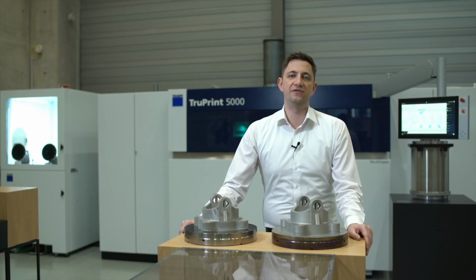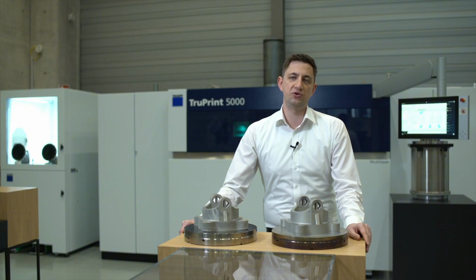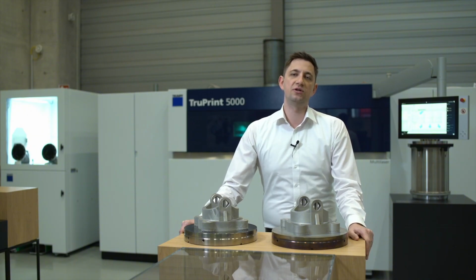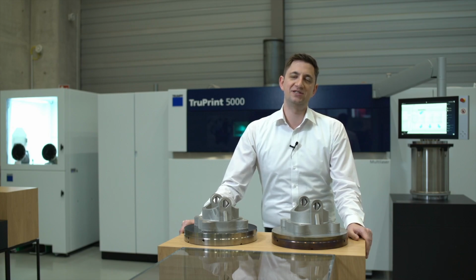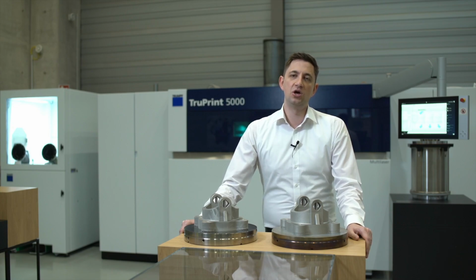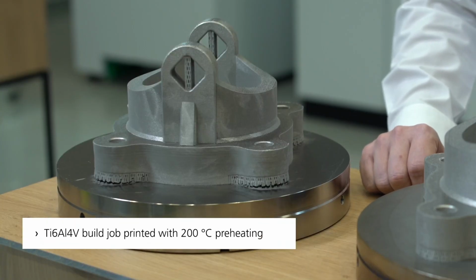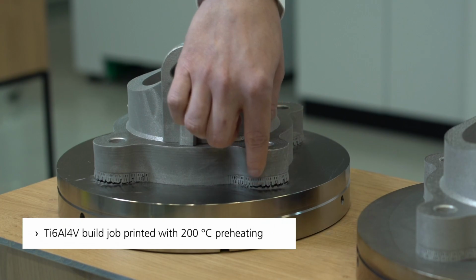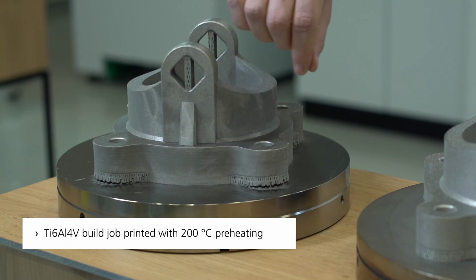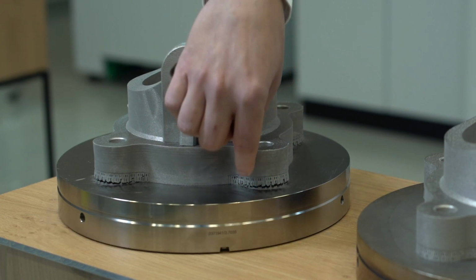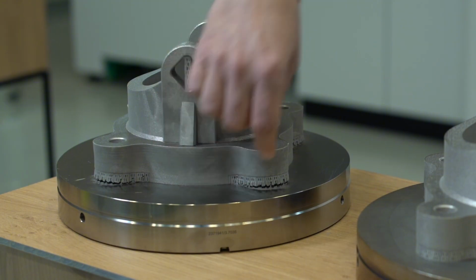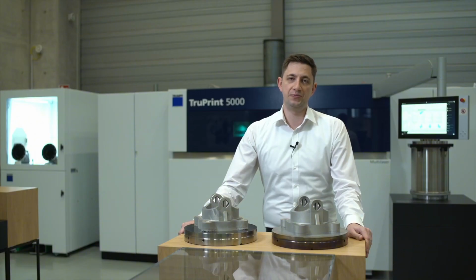To demonstrate the benefits of 200 degree preheating temperature, we chose one material off the chart that is especially widespread in the aerospace industry, titanium 6-4. What we know from this material is that the residual stress can become so large that the support structures break off and the part starts to suffer from warping and deviations. This typically leads to an abort of the build job.